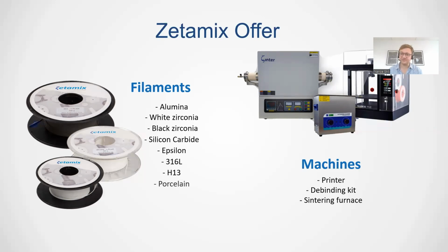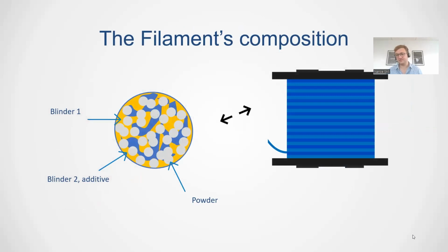So in general, how does our Zetamix material work? It's fairly simple. The filament is actually a mix of some thermoplastic binders, plastics to make it simple, and a powder with a very, very high volume loading of powder. We usually have more than 50 to 60% of the volume of the filament which is powder, which means in mass usually more in the range of 80 to 90%. That's a very, very high amount, and this is what allows us to go through the process afterwards.